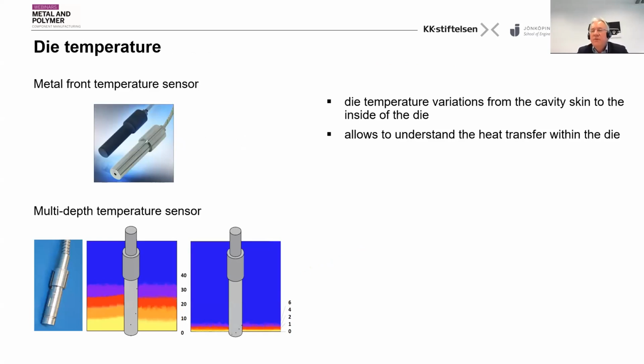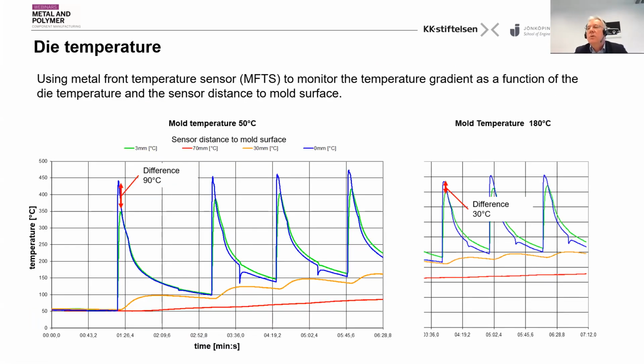Also die temperatures. Very crucial for the quality of a part is the metal temperature, but not only the temperature right at the surface, but also inside the die. And Electronics offers a sensor which gives you multi-distance reading. So right here, right here, and this shows you the reading you get out of it. On the left-hand side, you see the temperature curves. We are not yet in what we call quasi-steady state. And this is the temperature right at 0 millimeter, blue, basically the surface temperature of the metal. And then 3 millimeters in depth of the die, we have the green curves. You see a big difference.